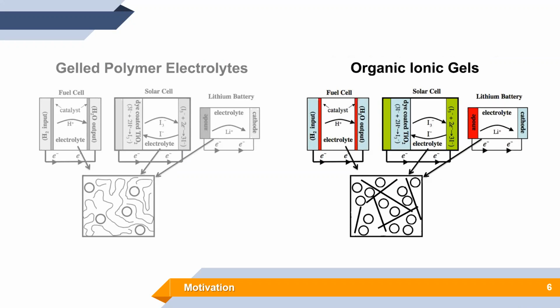Because when we arrive at the point where the battery is used and lots of defects are in the internal structure, we do not have to dispose of this battery, but just heat it up to dissolve the matrix, go to liquid state, remove all discontinuities, and gel it again by lowering the temperature. In the end, we have a new system with nominal parameters, which allows us to use it again. Also, the recycling process is much easier and less energy consuming.